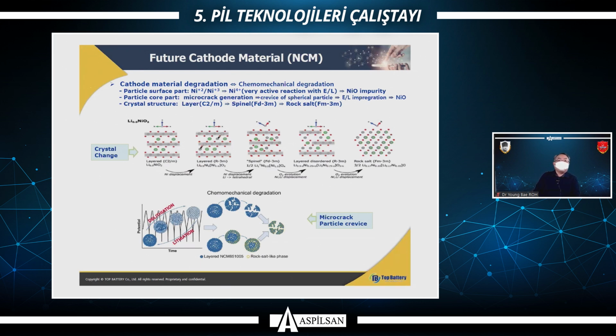This is cathode material degradation, especially of high nickel cathode material. It is known to be chemomechanical degradation. During charge state, the valence of nickel atoms in the particle surface part is changed from nickel 2+ to nickel 4+. This nickel 4+ is well known to react very actively with electrolyte. It leads to nickel oxide impurity, the rock-salt phase.